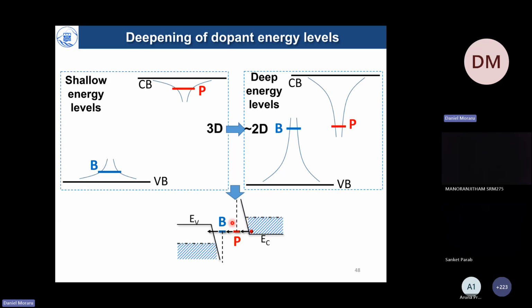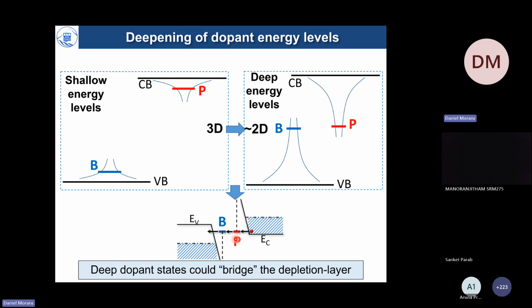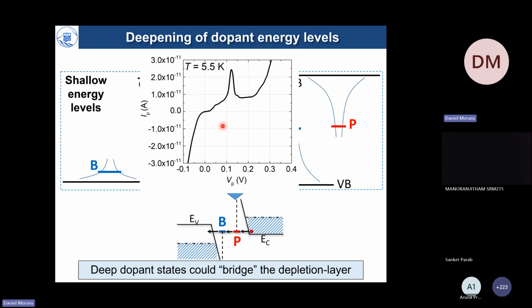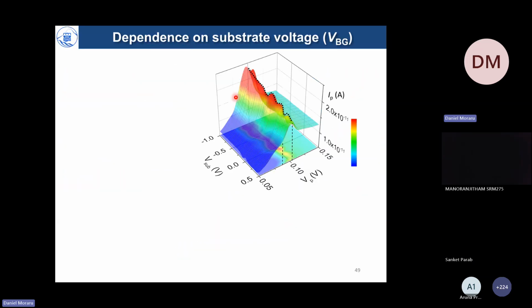These gap states become, surprisingly, stepping stones on the way of an electron from, let's say, the N plus lead towards the P plus available states. So this mediation by the dopant states is very important for fundamental applications of dopants. What we observed in our devices, in a very peculiar device, are characteristics similar to an Esaki diode: high reverse bias current, and an NDC peak in the forward bias regime, but also a very sharply enhanced current peak.